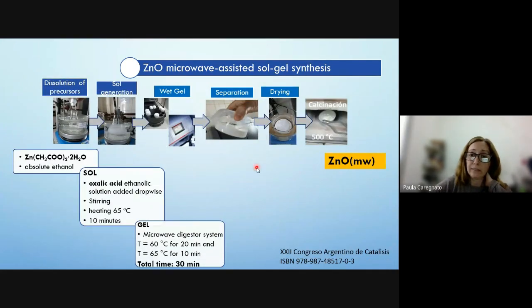The second group of catalysts was obtained by microwave-assisted Sol-Gel synthesis. The precursor was zinc acetate. The sol was generated by adding the oxalic acid ethanolic solution, stirring and heating for 10 minutes, and the gel was obtained in a microwave digester system with temperature control in a total time of 30 minutes. The gel was separated by decantation, and the solid was dried and calcined at 500 °C. The solid is named zinc oxide microwave.